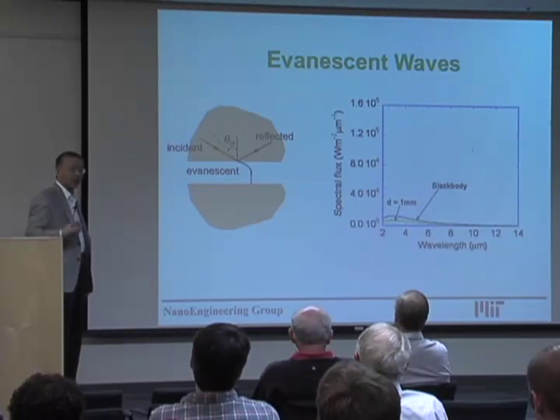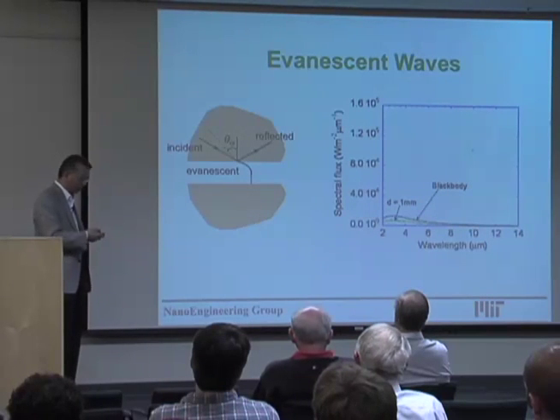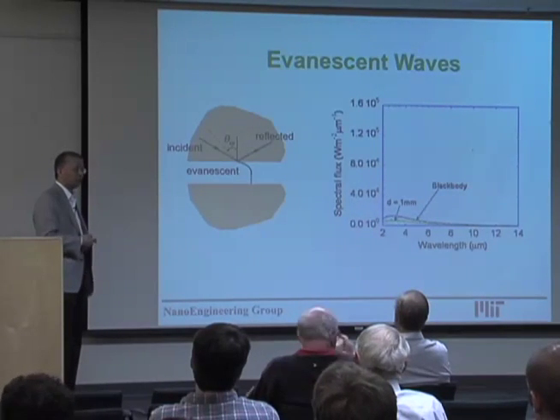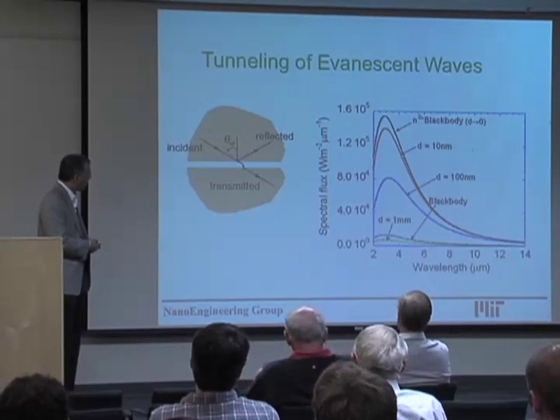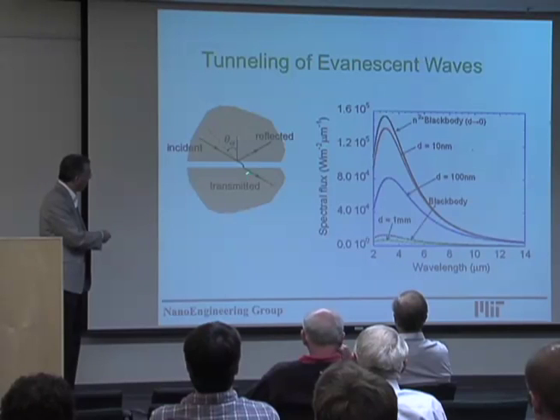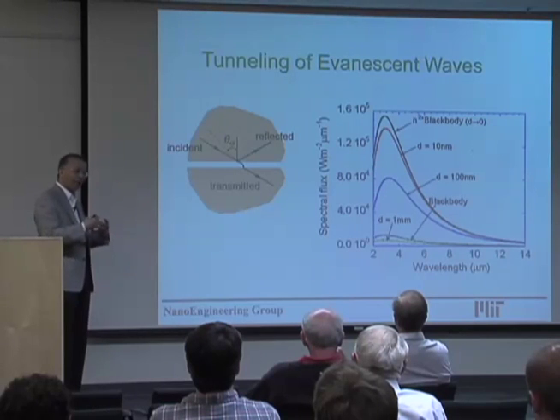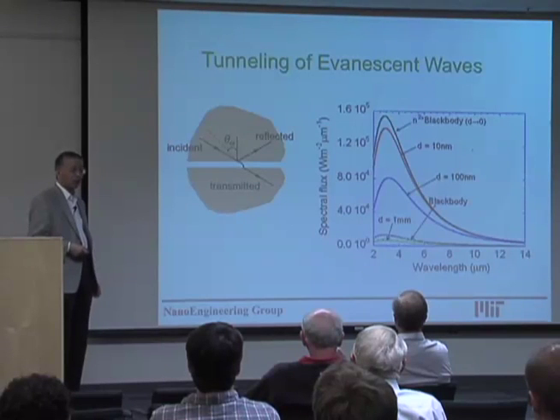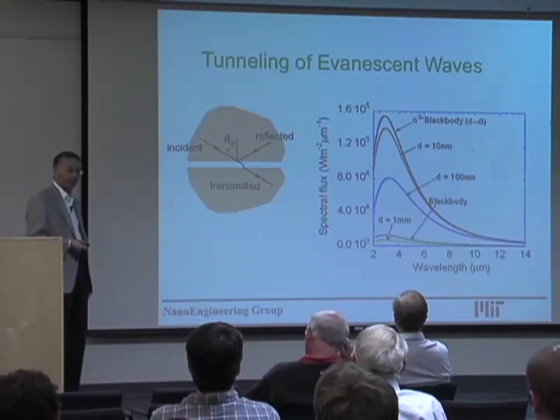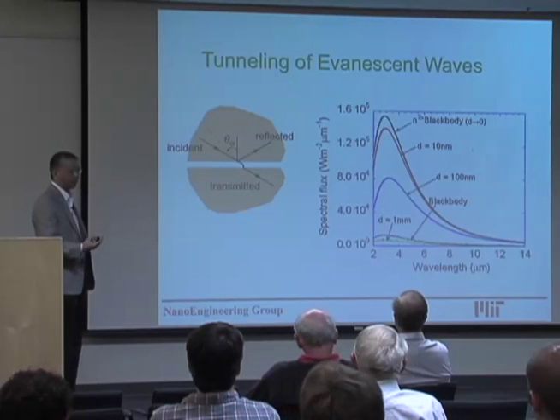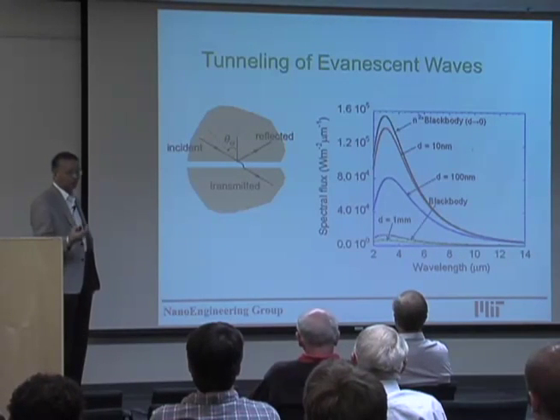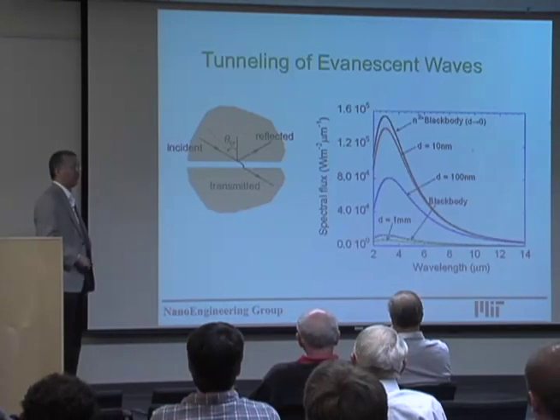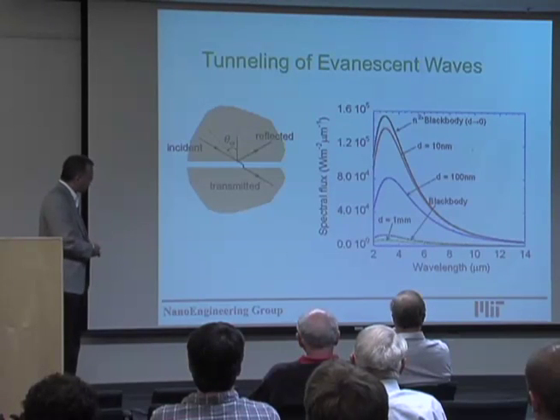A lot of people here work on photonics, and it's the same principle. It's just that here the source is the thermal source. So you have the tunneling, and in the limit, when the two surfaces get really close and contact each other, the blackbody radiation inside a material is proportional to the refractive index squared. So that's an n square effect. If we take silicon as an example, n square is about 10, the dielectric constant. So you say, okay, we probably can increase the radiation by a factor of 10. But that's not the limit.